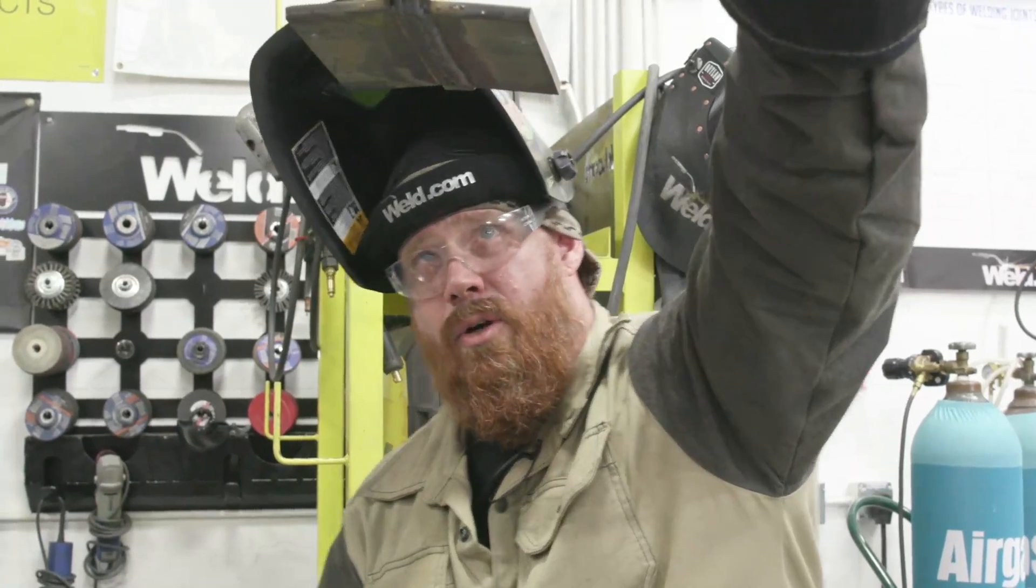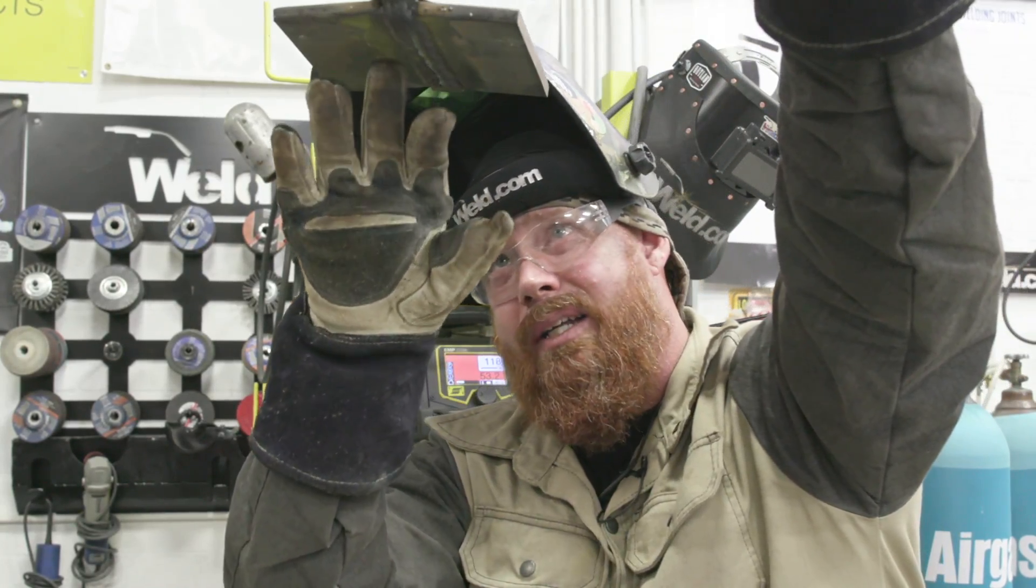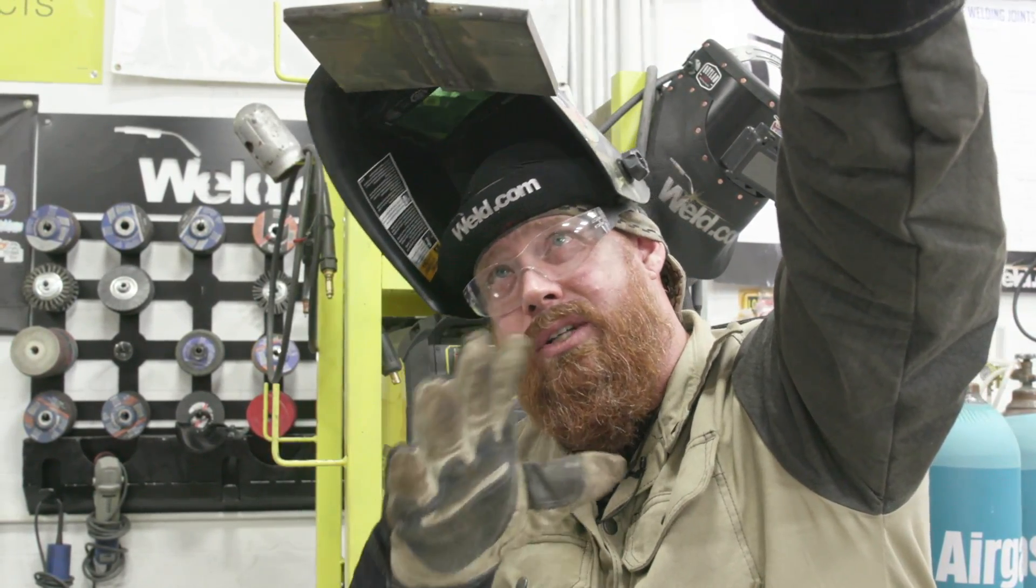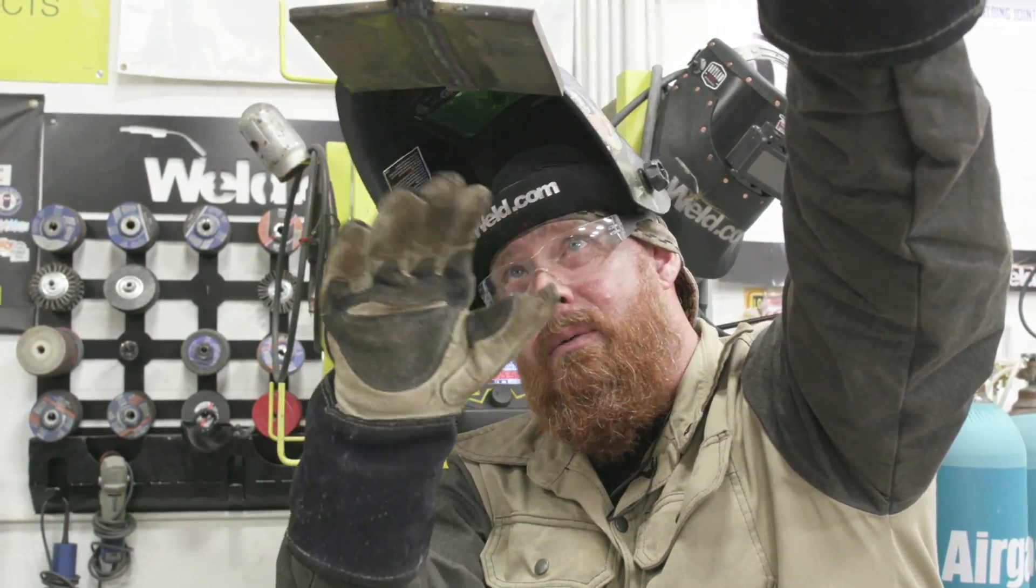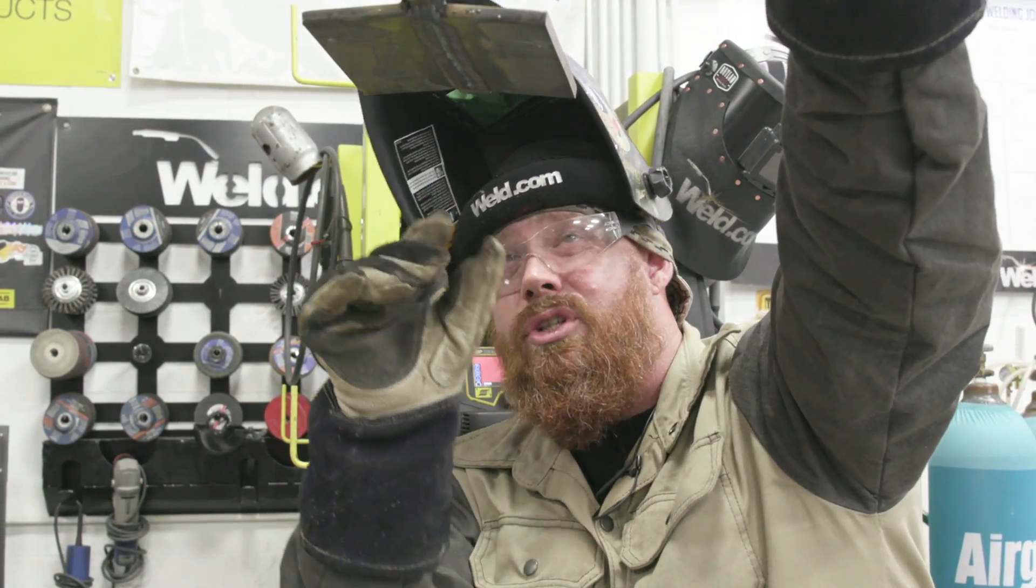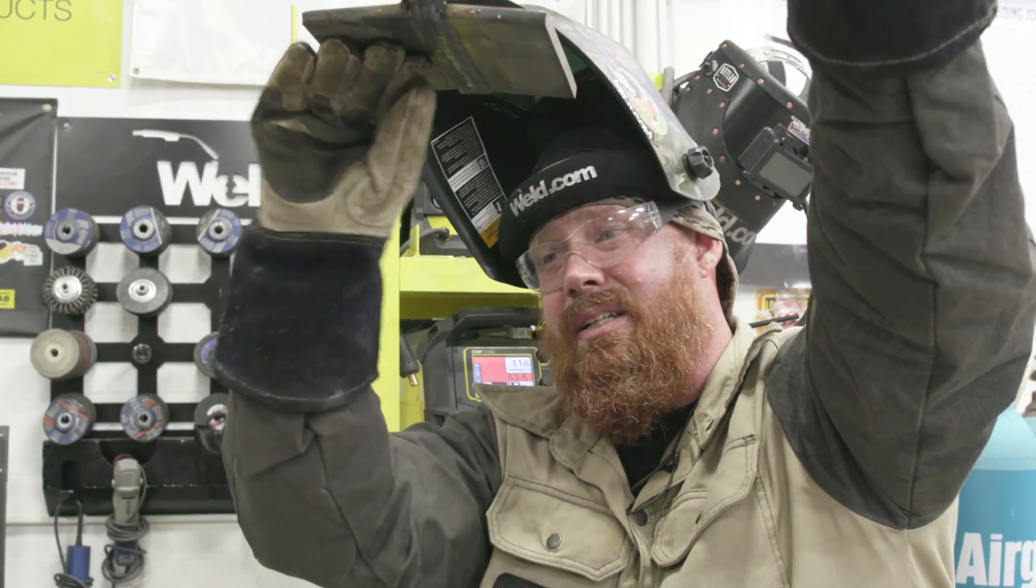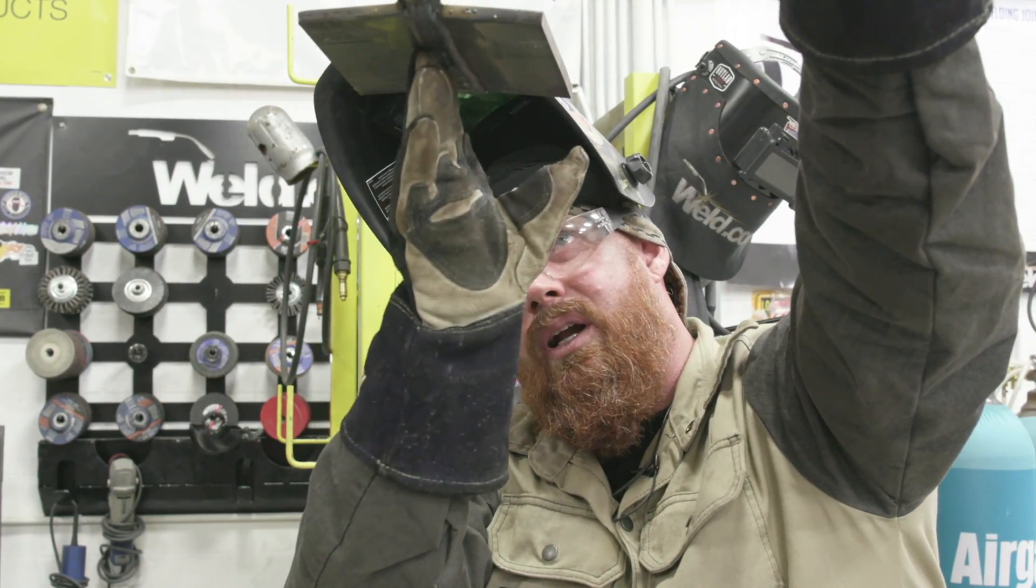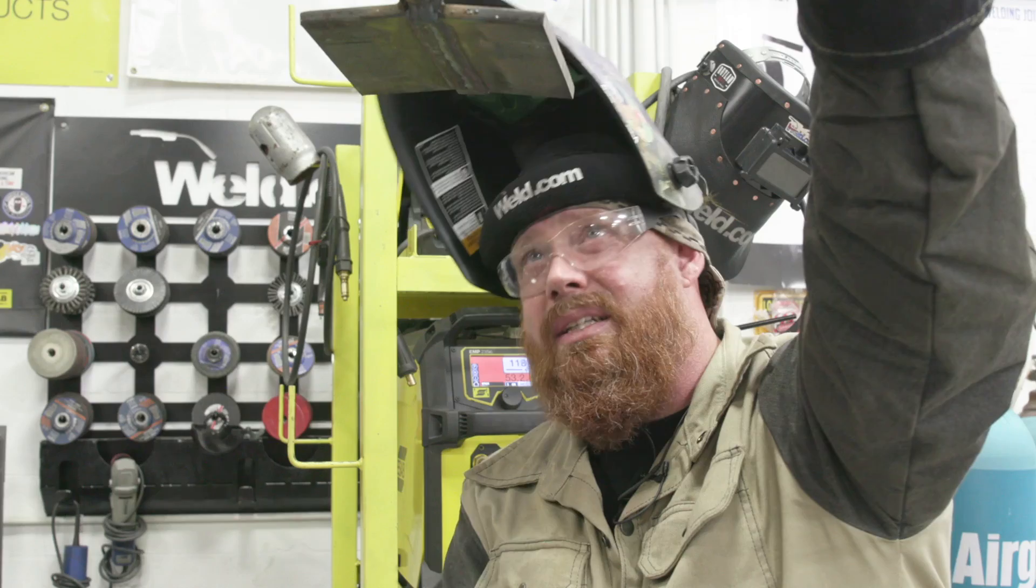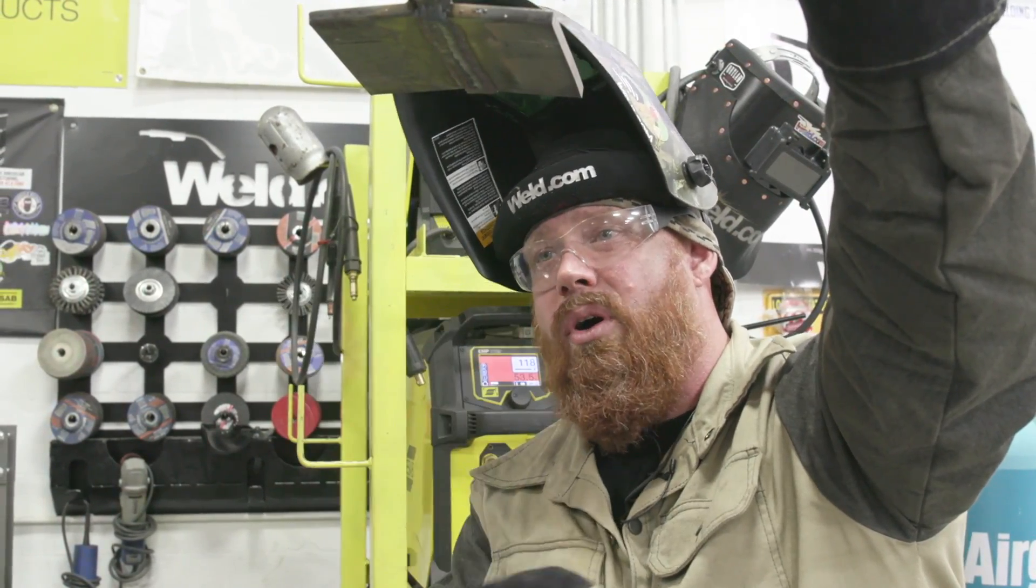Overall, I'm pretty happy with how everything turned out. It's nice and flat, don't have any low spots, don't have any undercut, so I don't have to worry about that. Bead appearance is good, a little bit wider than I'm used to because it's a half inch gap in the beginning. Usually I run about a 5/16ths on a double bevel, but overall I like it. We'll take it down, put some tools on it, find out where everything's sitting at. If everything's good, we'll process it and prep it for bend and see if we can pass this one.